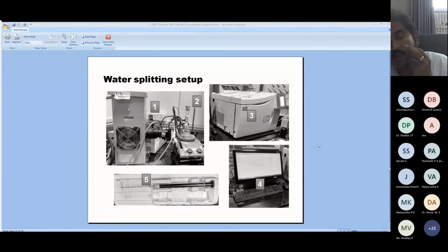At 0 minutes, there is no liberation of H2 and O2. After 30 minutes, again we take whatever gas is liberated with the Hamilton syringe, inject it, and observe a certain amount of H2 and O2. At regular intervals of time, 0 minutes, 30 minutes, 60, 150 and so on, we say that as the time increases, the amount of oxygen or hydrogen liberated also increases. Indirectly, we say that the material liberates H2 and O2. This is a very simple setup to generate hydrogen and oxygen.